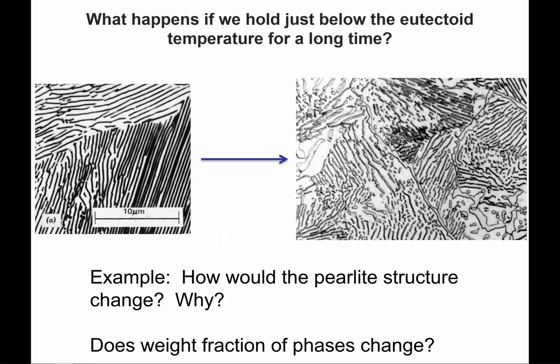All right, so let's just ask the question of what happens if we take a pearlite structure and we were to hold that at a high temperature for some time. So remember, this pearlite structure forms because of kinetics. When we form this layered structure so that we can keep up with the diffusion and be able to part the compositions, because the carbon is very high in these black layers that are the cementite, and quite low in the whiter areas, which are the ferrite. And so this is a kinetic case.